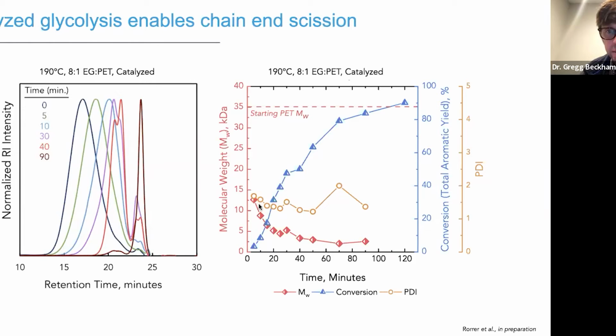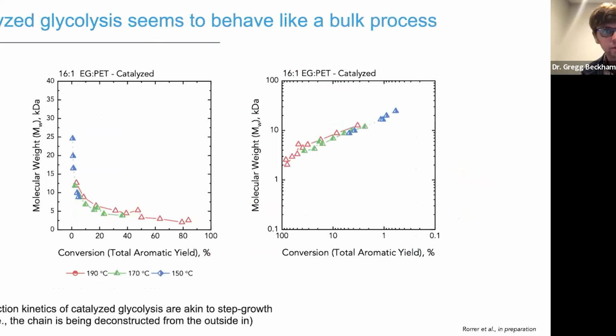And what you can see is a really dramatic drop-off in the MW right at the initial part of the reaction. Polydispersity, PDI, remains constant. And this is over just a few extents of conversion, up to about 20% extent of conversion. The MW has dropped from 12 down to about 6 or so. And so you get this really early and dramatic decrease in molecular weight.